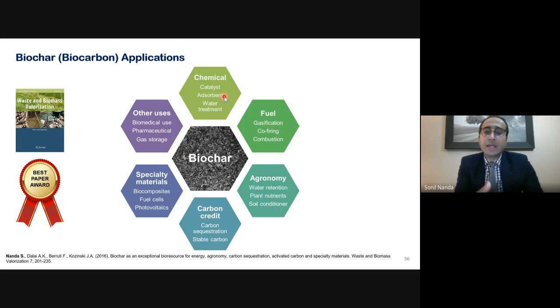Now, this porosity of the biochar can be further enhanced by activation processes. The activation can be through physical activation or different chemical activation. As a result of the chemical and physical activation, activated charcoal is produced, and the activated carbon can have a surface area many magnitudes higher than that of the biochar. For example, just a tablespoonful of activated charcoal can have a surface area of more than a cricket ground. You can imagine how large the surface area could be. For example, the activated carbon can have a surface area of more than 2,000 square meters per gram.